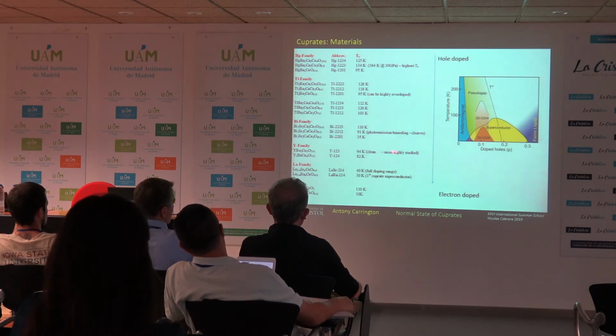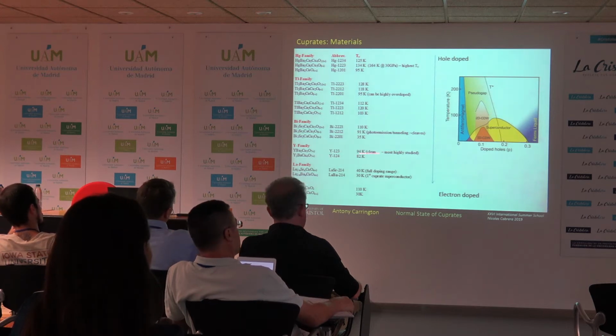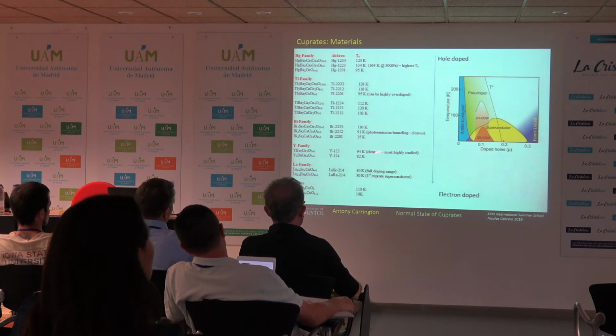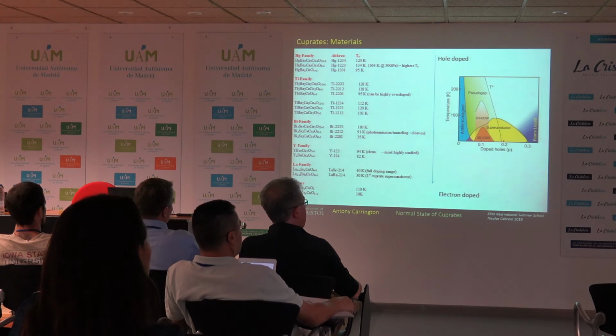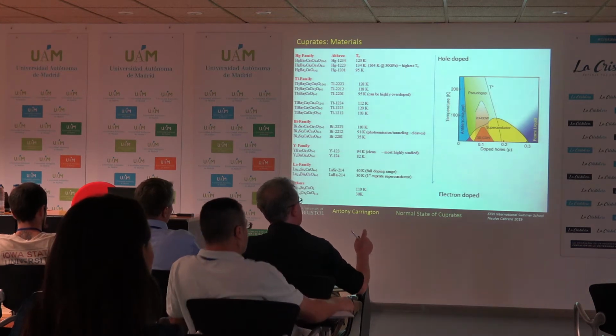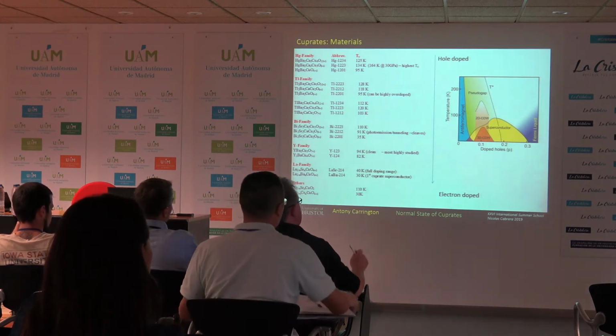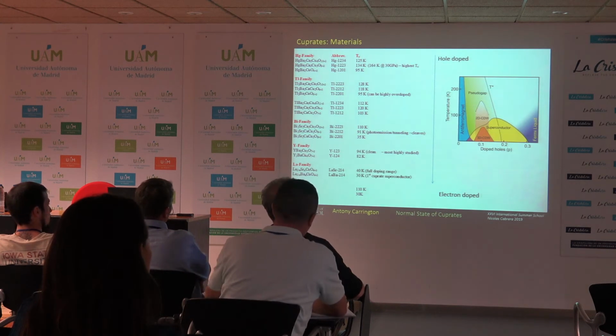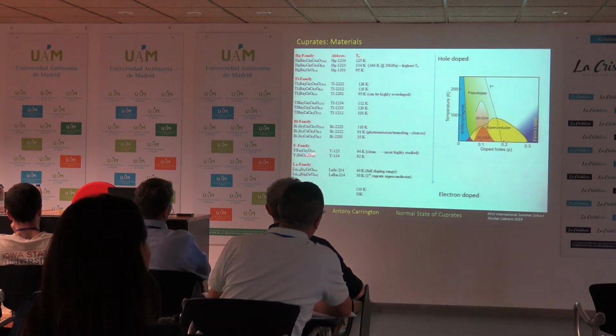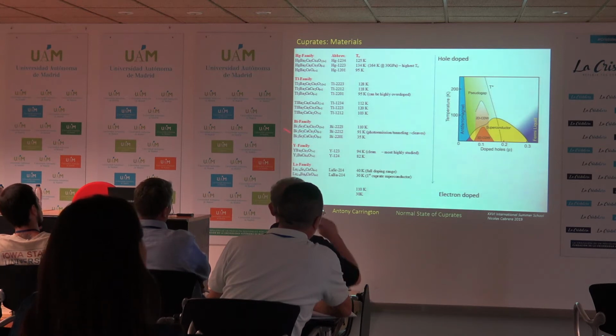Everybody's favourite is YBCO. Well, not everybody. Many people's favourite is YBCO. So this has got a high Tc and it's clean. That's its main unique selling point, as it were. When we say clean, we're talking about disorder in the copper oxygen plane. The nice thing about this one is that when you want to dope it, the dopants sit away from the plane. That is true for that one, and it's true for some of the other ones too.